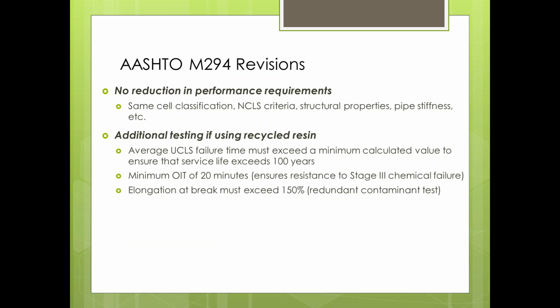So just to reiterate and to outline some of the changes in AASHTO M294 that will be published this fall, there's going to be no reduction in performance requirements whatsoever if you're utilizing recycled resins. It needs to have the same cell classification, the same NCLS or notched constant ligament stress criteria. It has to have the same structural properties, the same pipe stiffness. None of the standard is changing from that standpoint. What is changing is really an addition of a significant amount more testing if a manufacturer chooses and decides to use recycled resins.